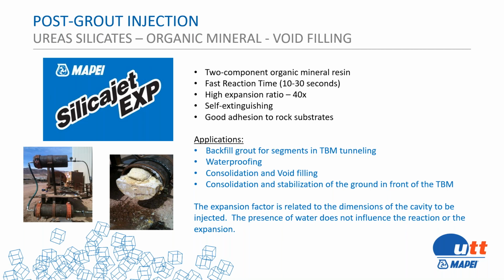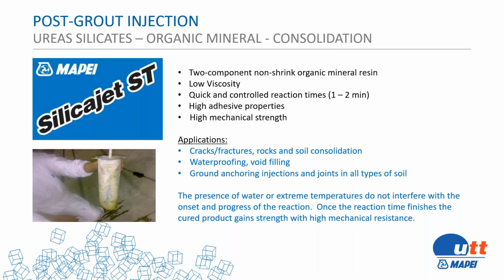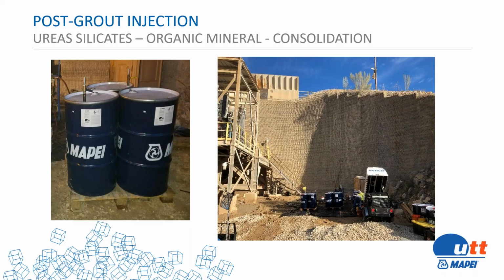Our silica jet, again, like our other families, we have three different family members of our silicate family. This one is high expansion, 40 times. We use it a lot for backfilling in the tunnels when we're using TBMs. The expansion factor would be relative to the space it's filling. Here we have the silica jet ST, which has a very, very high mechanical strength and high adhesive properties. So again, it's targeted for cracks and fractures. Again, you can use it in rocks and soil. So it comes in the drums, and here we have soil where it can be used very successfully in gluing all this rock or soil together. And if there's water, it will cure up and stop the water.